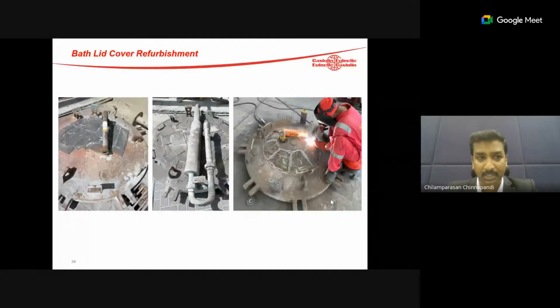This is one of the very unique applications, called a bath lid, where the tub has a cryolite process where the temperature will be 750 plus. The tub has refractories, but the top lid doesn't have any refractories because of the weight; it has to lift up and down. At a temperature of 700 degrees they pour the material, it comes to normal temperature, again goes up to 750 plus, and again comes to normal temperature. Because of that there is thermal shock, which leads to the sigma phase of the component, and that leads to cracks and punctures.